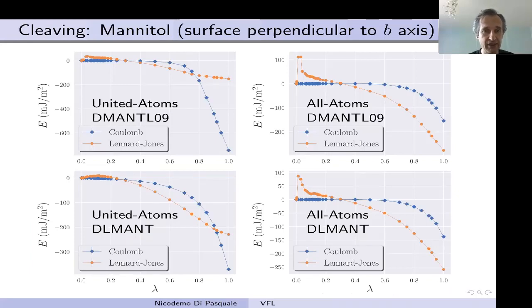So this is just the thermodynamic integration. Essentially what we are doing in the cleaving method is transforming a system where we start with bulk, so periodic boundary conditions on the sample in all directions, and then we gradually switch off interaction on the surface, which is on one of the surfaces. In this case, the result is for a surface which is normal to the b-axis. And switching happens gradually. We have a parameter which goes from 1 to 0. 1 means full interaction across the surface, and 0 means no interaction. So we essentially go from bulk geometry to slab geometry.